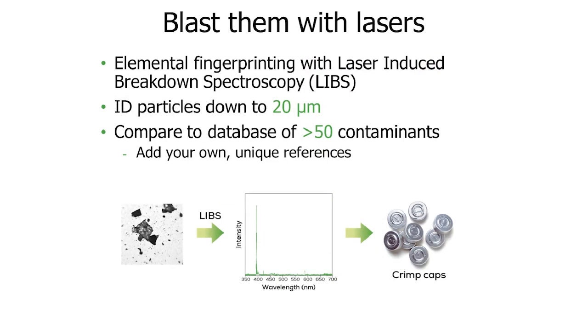For metallic and elemental particles, laser-induced breakdown spectroscopy, or LIBS, is able to get you that elemental fingerprint of the material. Just like the Raman database, Hound does come with a built-in, but still fully customizable LIBS database. While the default database in this case contains more than 50 common materials, you can fully customize this to tailor it to your process as well.